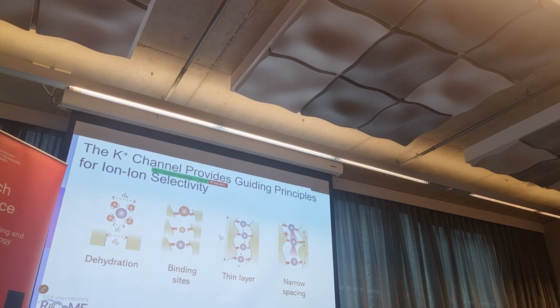And we need to have narrow spacing between the groups here. And this is what we call the knock-on effect, in which one potassium pushes the other potassium. They move not only because of this mechanism, but also because of the chemical potential gradient along the channel.